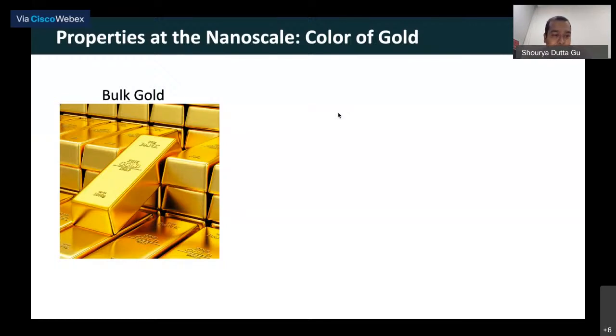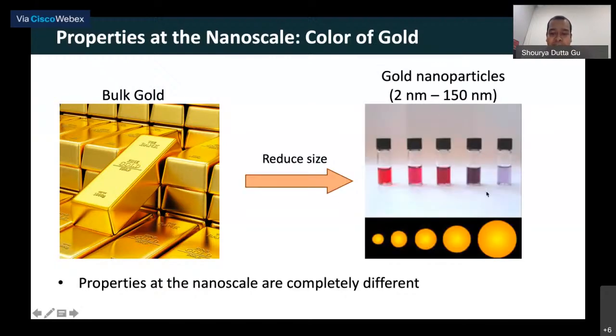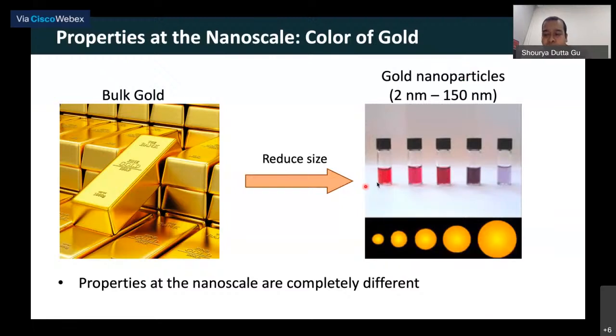If you take bulk gold, it has a nice yellowish color, which we all are very familiar with. However, if you reduce the size of gold, you can get very vibrant colors ranging from red to blue, and these colors are strongly dependent on the size. If you change from around 2 nanometers, on the left-hand side, to a bluish color because of a size of around 150 nanometers, you can get all these different variations of colors. This is what makes gold so interesting at the nanoscale. This is just one example of how nanoscale properties are so different from bulk properties.